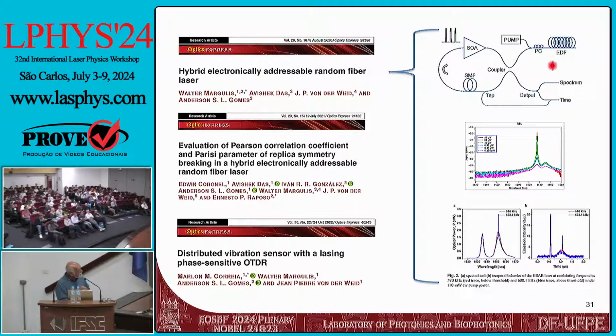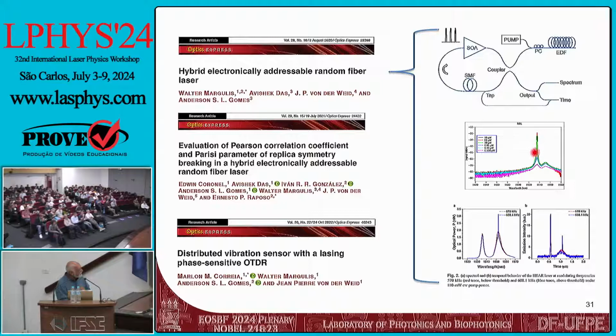This is the gain medium, the erbium fiber, and then you can choose a point inside, along the fiber. And this point is determined by the frequency that you use to synchronize your laser, to excite your semiconductor amplifier. So if you do that right, you can have a peak here at about 1.5 micrometers for the erbium fiber, and then you can exploit this in any position you like. That's why it's called electronically addressable.